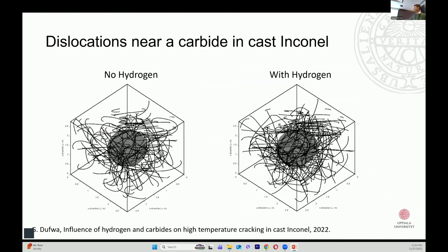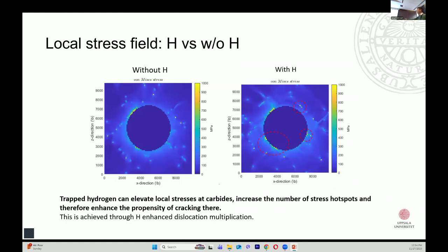And further, if we analyze the total stress field exerted by these two dislocation aggregates, we can see that for both cases, the stress field looks different. In the case with hydrogen, we are seeing a lot more high spot regions, meaning that hydrogen could promote the possibility of stress concentration, and it could increase the propensity of crack initiation. So this could be qualitatively related to hydrogen-promoted fracture.